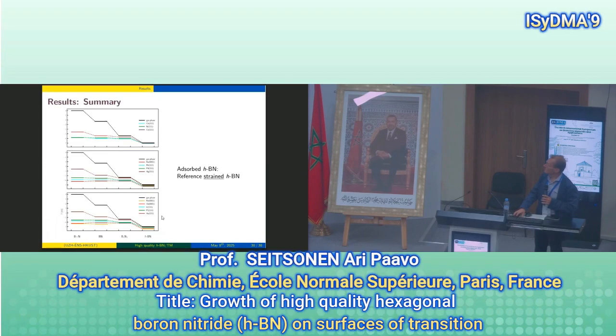What I want to show you is the energy diagram that we derive at the end. So we have the boron nitrogen adsorbed here, and the reference is in the gas phase. That's the 0 electron volt. I'm sorry, you probably can't see, there's no way to zoom. This is the energy scale in electron volts per one pair of boron nitrogen. The gas phase is the black one, and then three panels: 3d metals, 4d metals, and 5d metals. And then we studied the adsorbed atoms, dimers, hexamers, and the full monolayer.